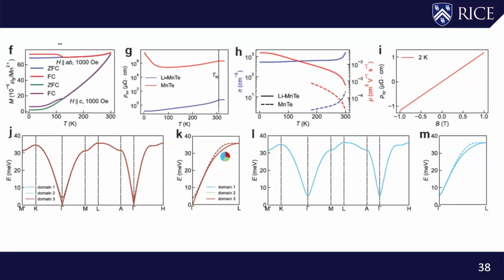And as soon as you dope the system, from zero doping to 3% doping, there's a dramatic transition from essentially a semiconductor to a very, very good metal. Of course, we confirmed the situation where the moment is really rotated along the c-axis. And in addition, we found that previously people who have done powder measurements have shown that you have an additional gap opening at the gamma point, and now the anisotropy becomes larger.